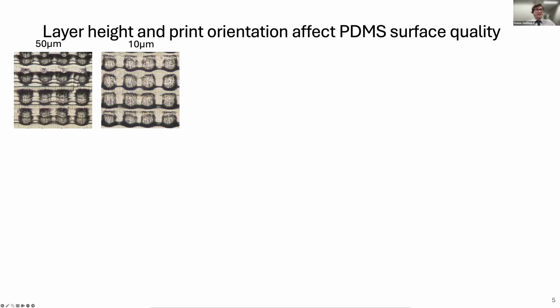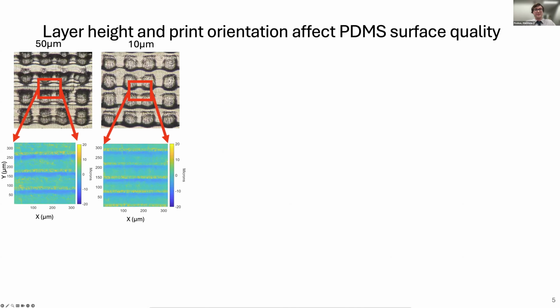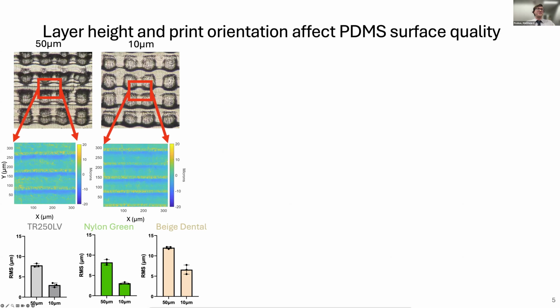We next wanted to explore how different printing parameters affected the quality of these PDMS. We started off with the layer height, comparing a 50 micron layer height to a 10 micron layer height. We used a technique called optical profilometry to reconstruct the surface of the PDMS and measure the variation or smoothness in that surface. What we found, consistently across different resins, is that when we move from 50 micron layer height to 10 micron layer height, surface roughness decreases. So we use the 10 micron layer height for printing.